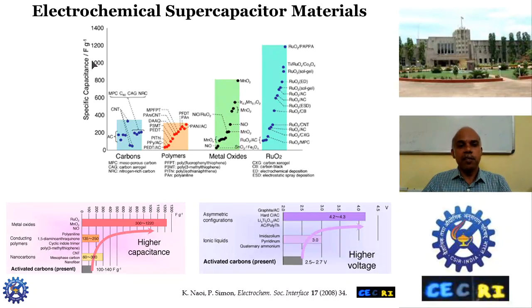If you look at the materials that have been used for electrochemical supercapacitors, it was carbon, in various forms like activated carbons, carbon aerogels, nanotubes or graphene. Here we can get about 300 farad per gram as specific capacity. Then came the polymers, like conducting polymers or different types of polymers, where you can also get around 300 farad per gram. In the case of metal oxides, manganese oxide itself, with different modifications, can show up to 800 farad per gram. And ruthenium oxide shows about 1200 farad per gram, and it can be combined with other polymers or other oxides.